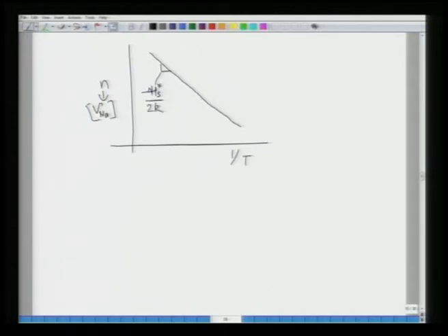If the sodium chloride was impure and you start coming from low to high temperature, up to a certain temperature the concentration of sodium vacancies due to extrinsic impurities is constant, because extrinsic impurity concentration does not change as a function of temperature.